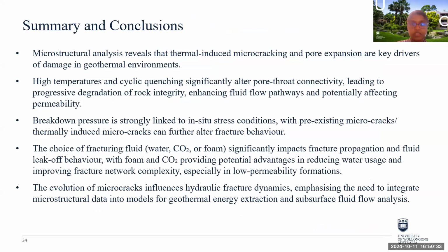Today, I presented some selected research relevant to thermal damage and fluid-induced fractures with special reference to microstructural analysis. Overall, thermally induced microcracking and pore expansion play an important role in damaging rocks in geothermal environments, affecting fluid flow and fracture. So the choice of fracturing fluid like water, CO2 or foam can also impact how fractures form, with foam and CO2 offering benefits in reducing water use and creating more complex fracture networks.